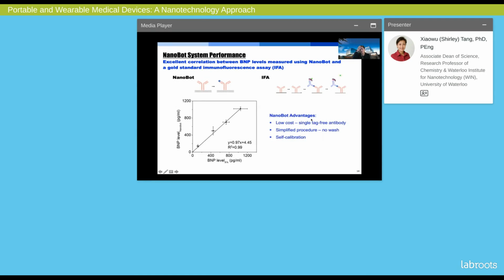The advantages of the nano-biosensor system are that, by using one single tag-free antibody, the cost is going to be dramatically lower. And the second, it has a much simplified procedure. It's a one-step real-time detection. No wash is needed because the transducer, the nanotubes, only responds to surface binding and disregards the BNP present in the solution. In contrast, immunofluorescence assays cannot distinguish between the fluorophores in the solution versus those bound on the surface, and therefore a thorough washing must be done prior to detection. A third advantage is that by using analytical chemical methods, the system can do self-calibration, unlike the standard immunofluorescence assay, where external calibration must be done prior to each quantitative detection.